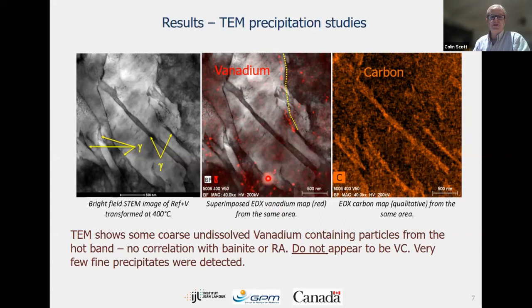Some of them are probably from the hot strip that were undissolved, and maybe along this line here, if they're in a linear type of constitution, then that might be from hot strip precipitation. But the rest of them we don't think are precipitates. And we didn't detect any very small precipitates that would be important for strengthening.